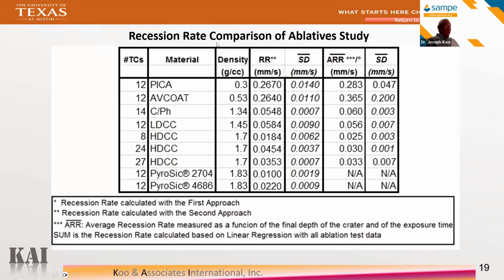We have been using this technology to measure and calculate the recession rate. Take a look at the density. These materials range from 0.3 grams per cc all the way to ceramic matrix composites at 1.83 grams per cc. What it means is this technology is very versatile. We're able to use it on a variety of TPS materials. That has been published, and we were able to develop this technology and use it in our materials development.